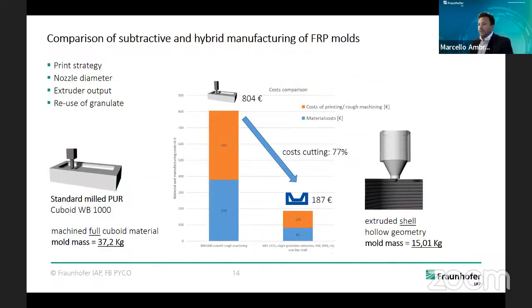And what is the big advantage of this technology compared to recent milling technologies or materials like polyurethane as a block material? We have a cost cutting of up to almost 80% using extruded shell and hollow geometries, which also allows us to decrease the weight and energy while producing the molds and the rotor blades, so that compared to a full polymer material of around 40 kilos, we decrease the mold mass to up to 15 kilograms.